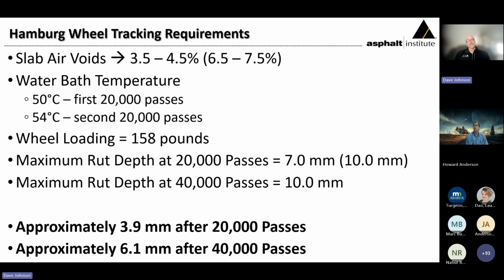A little bit more detail on the Hamburg. We already saw a number of these, and I mentioned how we made an adjustment to the air void content. There was that shift in the water bath temperature, the standard wheel loading at 158 pounds, and again, a total of just over 6 millimeters after the full 40,000 passes.